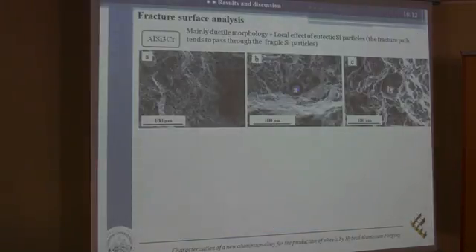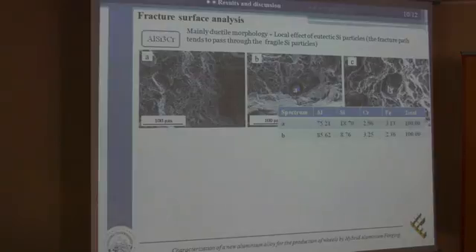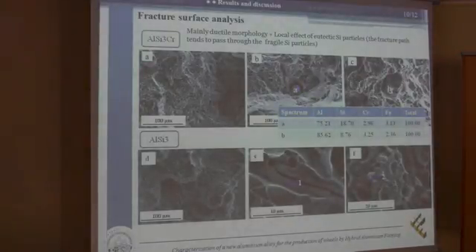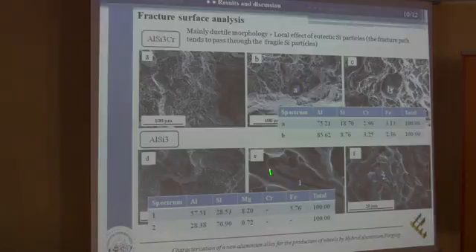From the observation by SEM of the fracture surface, it is possible to detect a mainly ductile morphology of the fracture, and also the presence of intermetallics containing chromium and iron. They detached from the matrix but did not crack, helping the ductile mechanism of the fracture. For comparison, we also analyzed samples from the same wheels but without the chromium addition. We found a similar general mechanism of the fracture, but in addition we found different intermetallics. As it's possible to see in figure E, iron intermetallic particles which cracked instead.